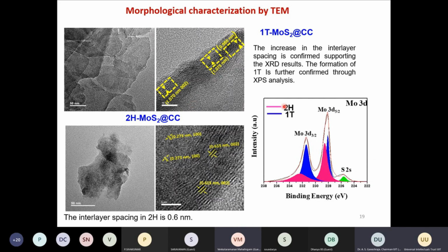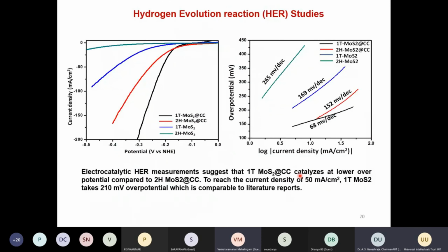Okay, this is further confirmed by the XPS, where you can see that the 1T phase has a slight shift in the peak. Basically, on the peak fitting, we found there is some contribution from the 1T phase of the material along with the 2H phase. So as I mentioned before, the 2H phase always coexists with the 1T phase.